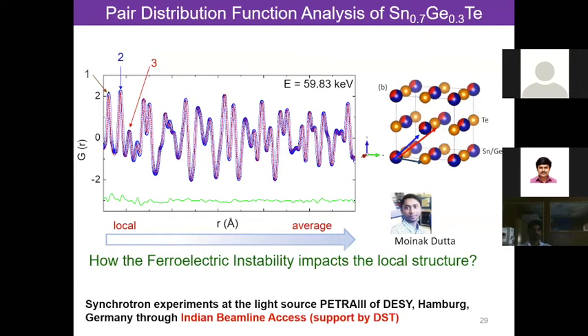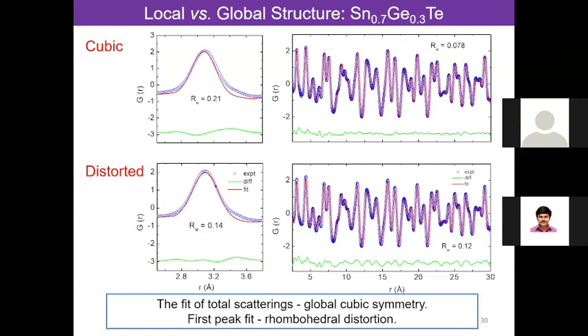We focused on this first peak, which is the germanium tellurium distance. You can see here with the cubic model, which is a rock salt model for the germanium doped sample, the global structure has an extremely good R value and is fitted well, but the local structure cannot be fitted well. The R value is high. Then we distorted the germanium along the rhombohedral direction, the 1-1-1 direction in a cube. The local structure fitted extremely well. That means germanium is distorted locally, but the global structure is not fitted well. The R value increases.